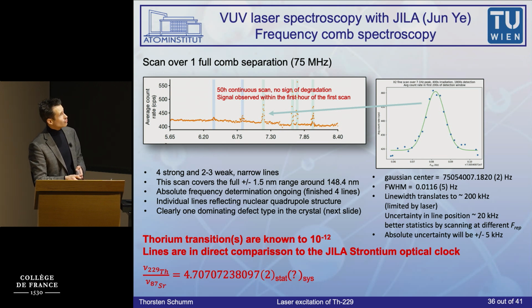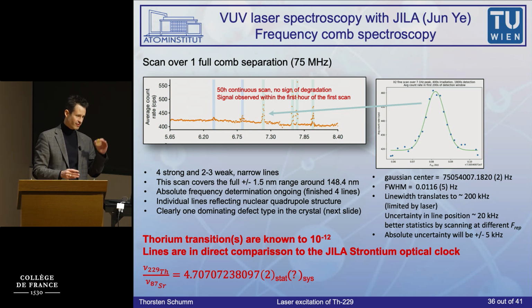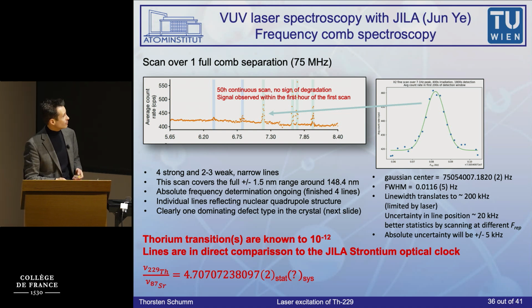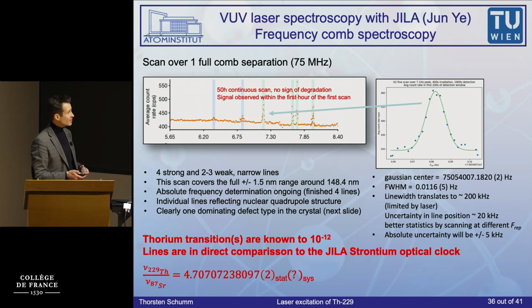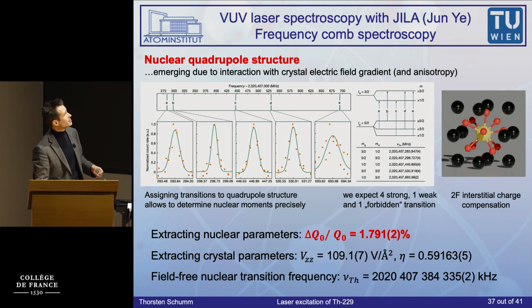The good thing about Jun Ye's laser system in Boulder is that it's automatically linked to one of the world's best atomic clocks, the strontium clock. So we actually have performed a comparison measurement of the thorium with the strontium clock. And that was, again, published quite nicely. So what about these lines?